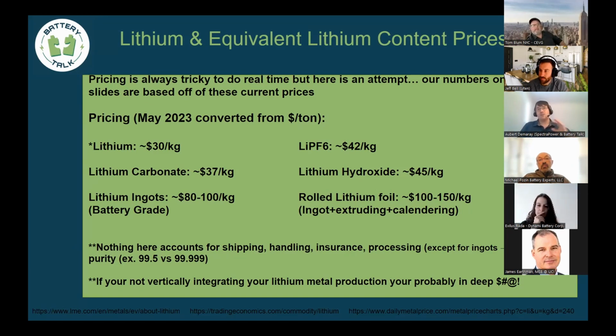But these are kind of the raw pricing right now of what you can find for the quantities in ton scale, for these materials in ton scale. So we just took those, reduced them down to kilograms. Nothing here accounts for the shipping, the handling, the insurance, the processing, except for the ingots to foil, which you have to do, or different purity grades and costs and requirements. And one of the bigger takeaways you'll see soon is that if you're not vertically integrating your lithium metal production, you are probably in a lot of trouble.